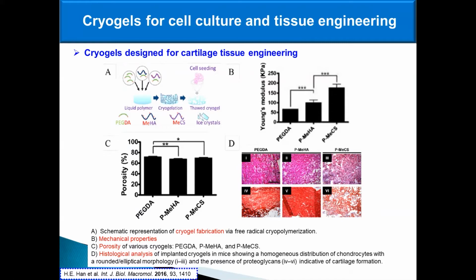Specifically, Han et al. developed a highly porous cryogel fabricated from either methacrylated chondroitin sulfate or methacrylated hyaluronic acid cross-linked with polyethylene glycol diacrylate. The resulting scaffolds exhibit a highly interconnected microporous structure with large pores and about 75% porosity. The histological analysis of the gels implanted in mice showed a homogeneous distribution of chondrocytes with a rounded elliptical morphology and the presence of proteoglycans as an indicative of cartilage formation.